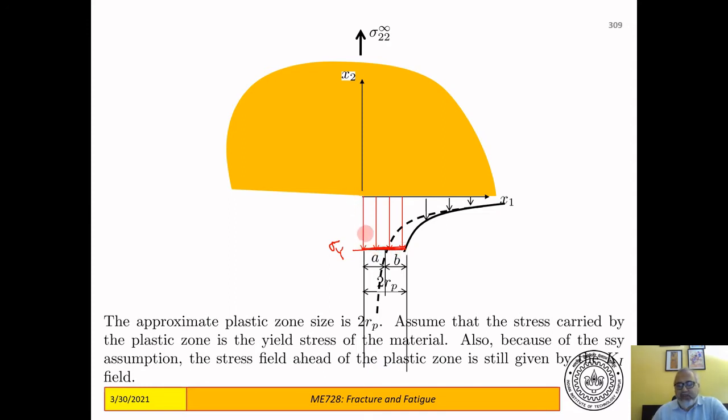and then under this flat region the maximum stress has been attained. So under the flat region, the maximum stress attained will be sigma y constant, and then again the shifted form of this curve will start to take effect, and we will have this 1 by square root r variation again at the end of the plastic zone. So this length is a measure of the size of the plastic zone that we are going to have in front of a crack tip when it is subjected to a load equivalent to a stress intensity factor of K1.